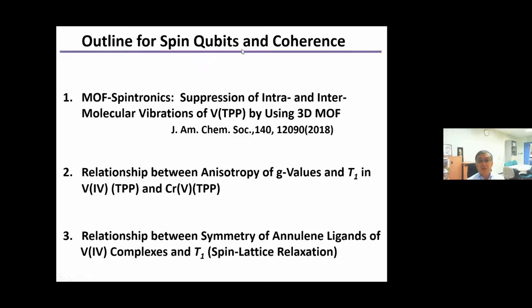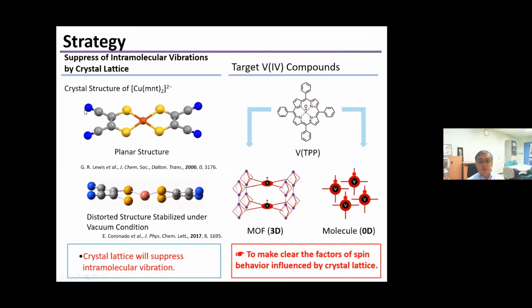So our target is MOF spintronics. There are 3 topics, but due to the time limitation, I focus on MOF spintronics. This means the suppression of intra- and intermolecular vibration of oxo-vanadium TPP by using a 3D MOF, published in JACS. In the crystal structure, Cu(mnt)2 is planar. However, in the vacuum condition, this Cu(mnt)2 is distorted. So the crystal lattice suppresses intramolecular vibration.